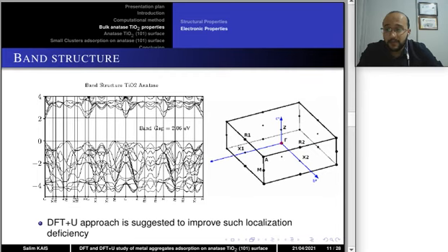The band gap was estimated with an error of 32.81% relative to the experimental value. It is known that the band gap of transition metal oxides is underestimated with conventional DFT approaches. They are inappropriate for characterizing semiconductors with open shell electrons localized in the d orbital, which is largely due to the self-interaction error in approximate exchange functionals.